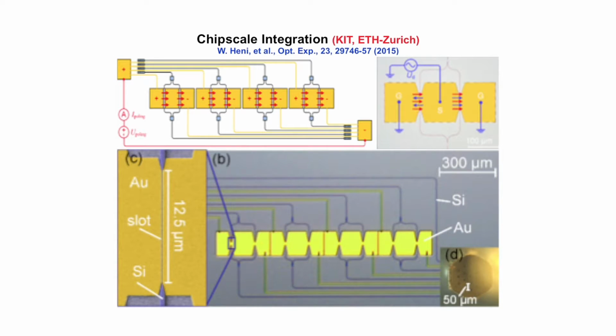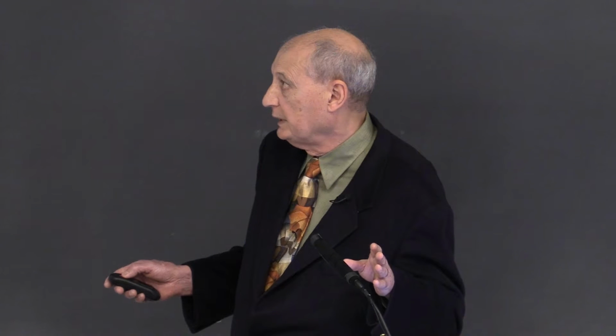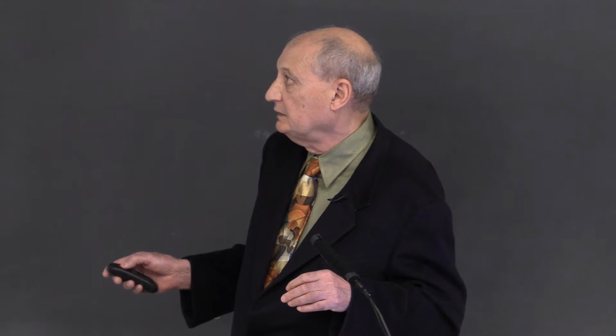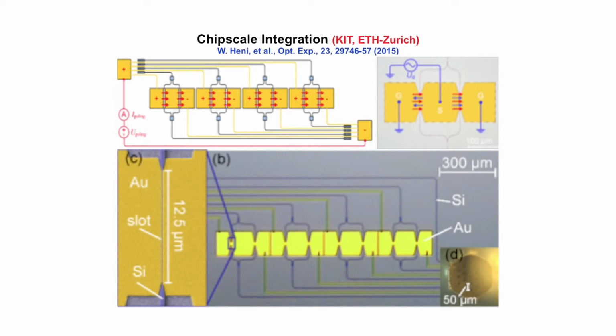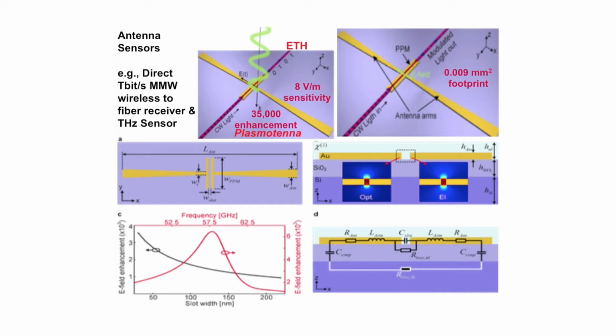We've also implemented large-scale integration where you're putting a lot of modulators on a single chip. Now, one of the issues with doing this is obtaining uniform poling for each of these modulator devices. And this shows you one example of a parallel poling configuration that's worked very successfully in doing this. In fact, we get a 100% yield with very little variation in performance from modulator to modulator. This shows the connection of electrical inputs for the actual drive of a modulator in this multi-modulator configuration.